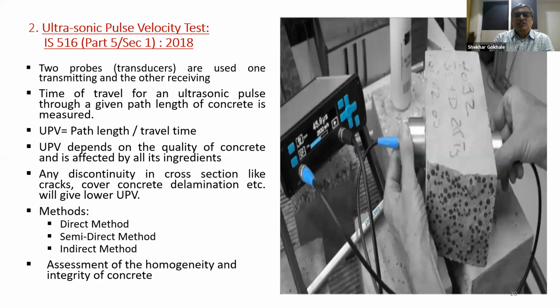The second test is the ultrasonic pulse velocity test, wherein there are 2 probes. We can see in the diagram, there is a concrete block, and on both sides there are 2 probes. One probe is used to transmit the pulse, and the other is for receiving it. The time of travel of an ultrasonic pulse through a given path length of the concrete is measured. The thickness of this block is the path length, and the travel time is measured in the display. The path length divided by travel time gives us the UPV.